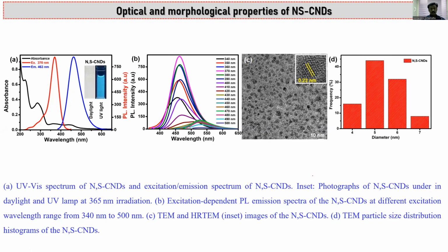Also, for the prepared carbon dots, the photoluminescence excitation is from 340 to 500 nanometer. In the previous chapter we confirmed the excitation dependence because there were no changes in the stability of the carbon dots, but this carbon dot is entirely different from those studies. So we get excitation-dependent wavelengths from 340 nanometer to 500 nanometer. Another one is the morphological studies.